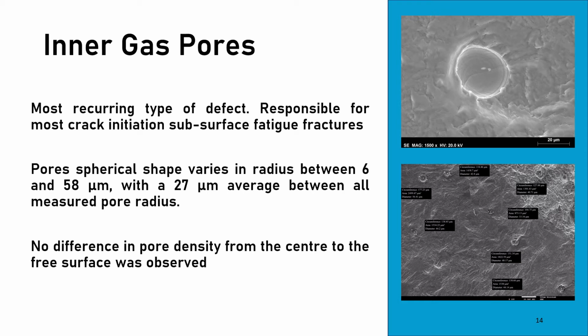Now, they present a spherical shape, so their radius was measured, which varied between 6 to 58 micrometers, with an average of 27 micrometers between all measured pore radii. No difference in pore density from center to free surface was observed in all conducted measurements.